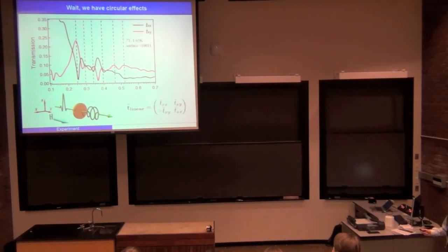And then we realize that when we apply magnetic field, as I mentioned, the spins would be precessing, and as a result, it would have preferential absorption for circular polarized light. So we would have circular effect. As a result, if we send in a linearly polarized light, the transmitted light would be elliptically polarized. So in order to get full information, we need to not only measure the transmission along this direction, we also need to measure the transmission in the perpendicular direction. This is what we did for the red curve, is transmission in the perpendicular direction.